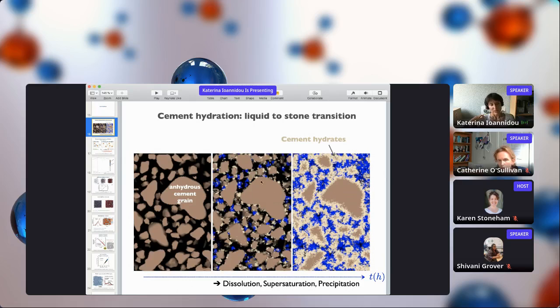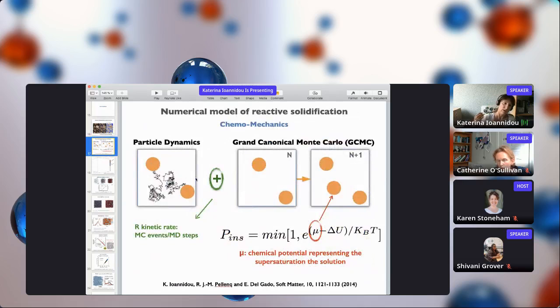So here what we did is assume we have our simulation box between two grains of cement. We have a pore solution which is supersaturated, and we are going to model the precipitation of calcium silicate hydrates.